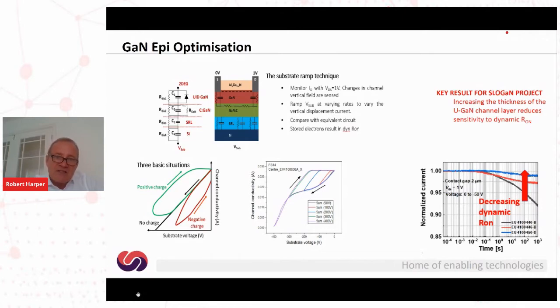So gallium nitride has a different lattice constant; the way that the atoms are spaced within the crystal structure means that they don't necessarily align with the silicon crystal that we're growing on. So we need this engineered layer, called the stress relief layer, as a first layer. There's a doped gallium nitride layer shown in green there. This is carbon doped gallium nitride, and on top of that we grow the channel layer, which is pure and undoped gallium nitride.